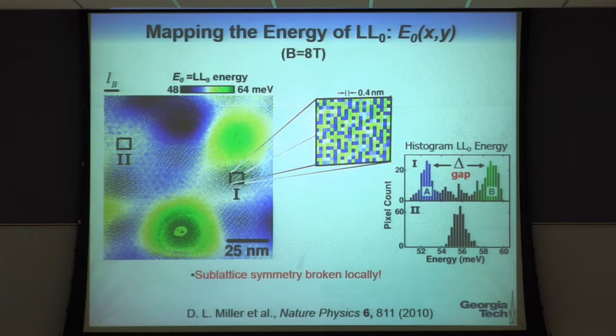Now, when we did this work, we actually sort of expected to see those types of features. What we didn't expect is that in some regions, we found a dramatic atomic scale change in the Landau level energy. So as we went from one point to another, the Landau level energy changed by tens of millielectron volts, which for these temperatures was a big energy. So what we were seeing was spatially, there's a gap here in energy between these peaks, which I'll label A and B. And over here, at a different point on the surface, there was no gap.